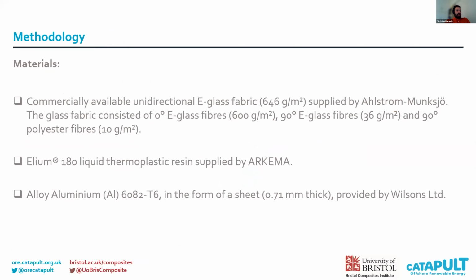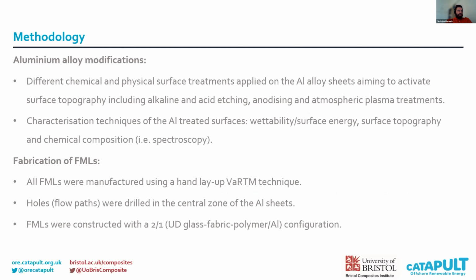So, very briefly, in order to fabricate these fiber metal laminates, we used a commercially available unidirectional E-glass fabric, Elium 180 grade liquid thermoplastic resin supplied from Arkema, and aluminum alloy 6082 T6 is the grade, in the form of a sheet 0.71 millimeter thickness. Activation of the surface topography of the aluminum alloy sheets was performed by applying different chemical and physical surface treatments, including alkaline and acid etching, anodizing, and atmospheric plasma treatments. Characterization of these activated aluminum surfaces was performed using wettability, surface energy, and surface topography measurements. Also, spectroscopy was acquired in order to investigate the chemical composition of the treated aluminum surfaces in terms of the functional groups.